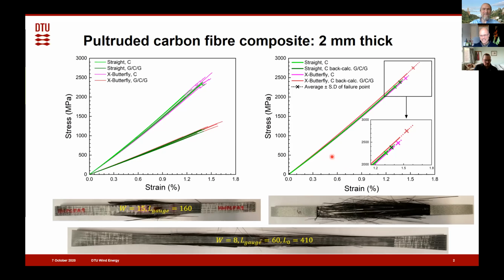Okay. But the size effect will only, you could say, take into account 1/4 of the measured improvement of the strength going from the rectangular sample to the butterfly sample. So that is in short the conclusion from the size effect.